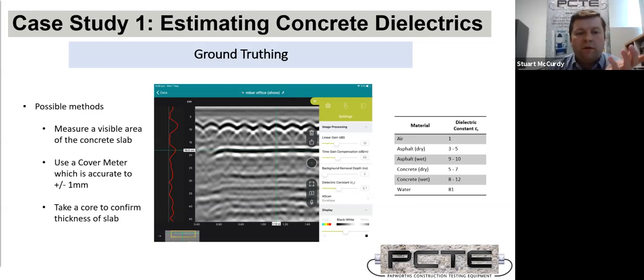All right, so here's ground truthing. There's three ways to do it. Pick an area you can see the thickness of the slab. You could take a core to confirm the thickness, or you could take a cover meter, which is accurate to typically plus or minus 1 mm, and use that for the top layer of reinforcement to get an actual measurement of something. In this case, I could see the slab was 180 mm thick at one point. So I left my crosshair on the bottom of the slab. And then I adjusted the dielectric from 7 up to 9.7, and that changed my slab thickness to be 180,